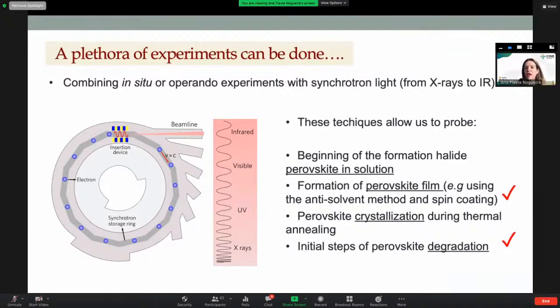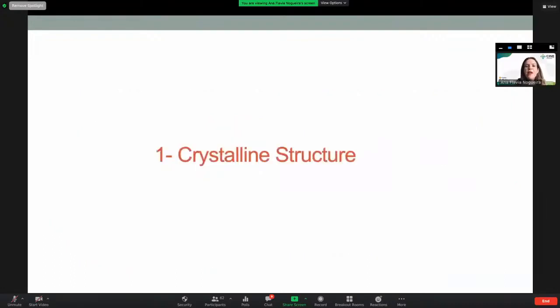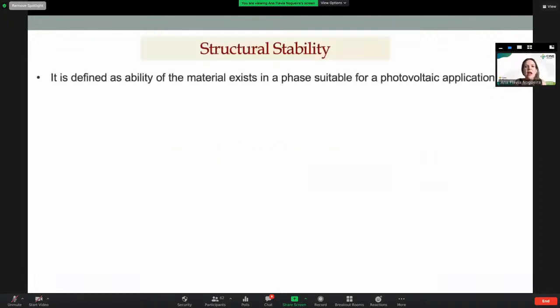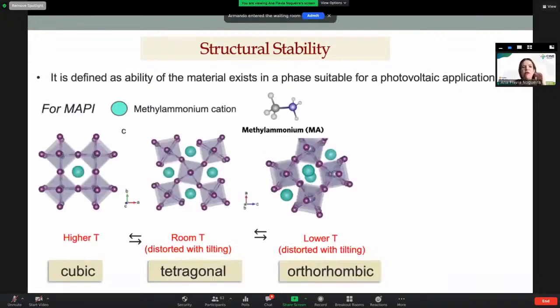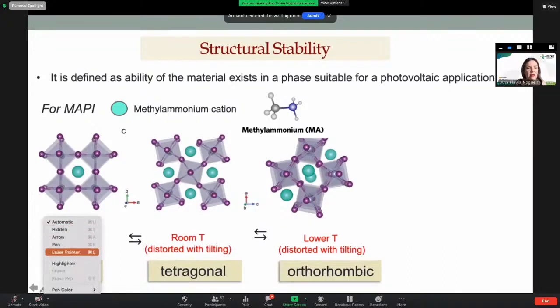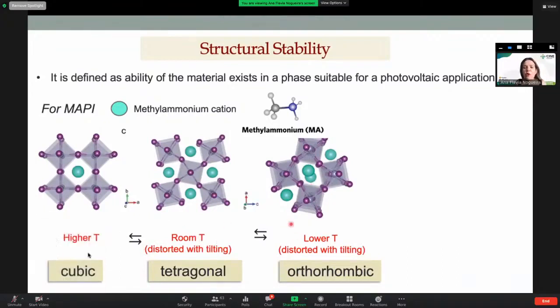from our group, for the formation of the perovskites and degradation. But let's take a look at the crystalline structure, because this is something that is really important for those that want to initiate in the field of perovskites. How can we define structural stability? Structural stability is defined as the ability of a material to exist in a phase that is suitable for photovoltaic or any other application. In the case of MAPbI3, which was the most studied perovskite, you can see here that at room temperature you have this MAPbI3 in a tetragonal phase. At higher temperature it goes to cubic, and at lower temperature, orthorhombic.